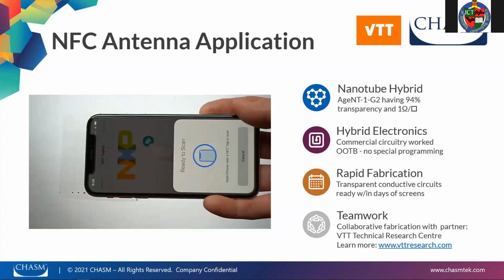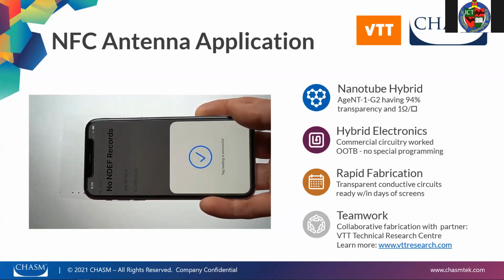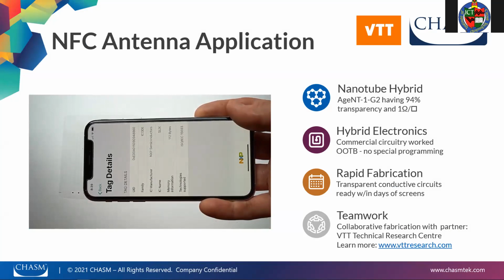Here's an example of a near field communications antenna for mobile applications. This was fabricated as a collaboration with what we call our preferred integration partners. In this case, it was VTT Technical Research Center in Finland. This device used our AgeNT-1-G2 nanotube hybrid for the transparent conductive antenna circuit. At 94% transmissivity, the circuit is visually transparent even when it's not backlit. Using commercially available hybrid electronics that VTT applied to the circuit, they used standard assembly and programming methods. There was nothing special that was required in order to produce this circuit, and it worked out of the box the first time it was created.